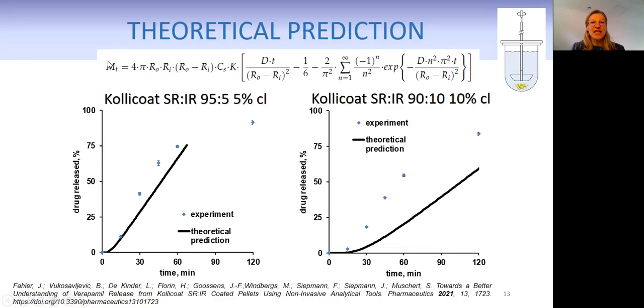So drug amounts released over time are actually a function of the film coating thickness, the outer radius minus the inner radius, and the solubility of the drug. So that's why we only did this theoretical prediction for acetate buffer pH 3.5, where we had perfect sink conditions. K is the partition coefficient, which is the affinity of the drug between the polymeric film coating and the water-filled core. And D is the experimentally determined diffusion coefficient, meaning the behavior of the drug molecule within the polymeric network.